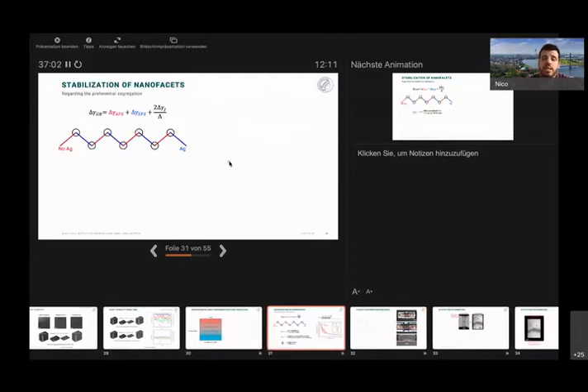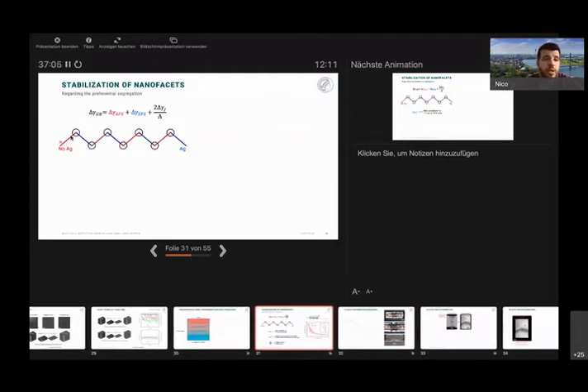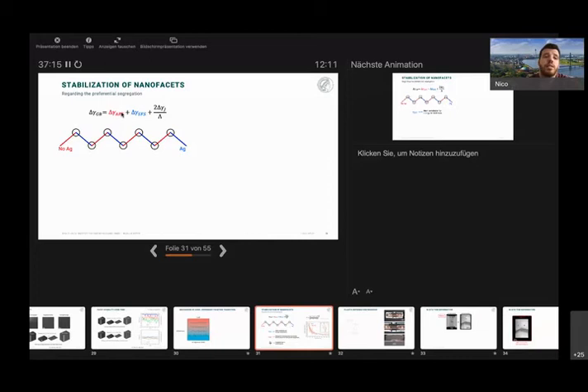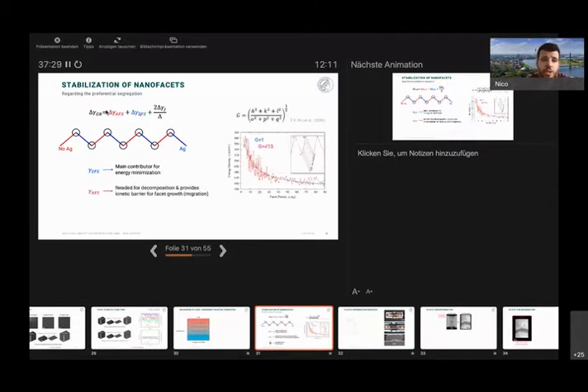And why is this? Well, we think it's because of different things. We have the grain boundary here schematically with no silver and silver containing segments and the junctions. And if you look at the grain boundary energy change, it is related to the asymmetric portion, the symmetric portion, and the junctions. So this portion here is the main contributor, because here silver goes and changes the energy, minimizes it. This portion here, we don't have any silver going there, so it's not changing the energy there.